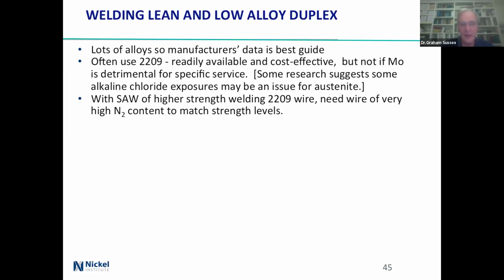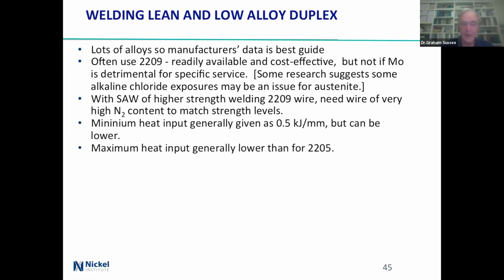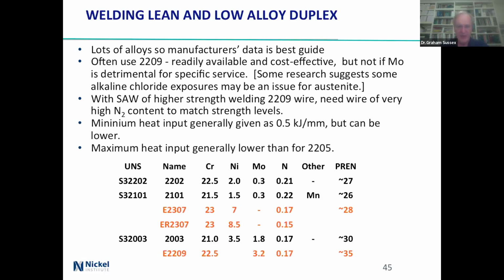For submerged arc with 2209, your wire needs to have pretty high nitrogen content to match the strength levels, because otherwise you won't have enough. Minimum heat input is generally given as 0.5 kilojoules per millimeter, but can be lower, provided you have got enough heat in there to actually get the solidification properly. And maximum heat input for the lean and low alloy generally is going to be lower. And here's a bundle of suggestions, straight out of the texts, looking at the alloys there and the electrode or rod choices.